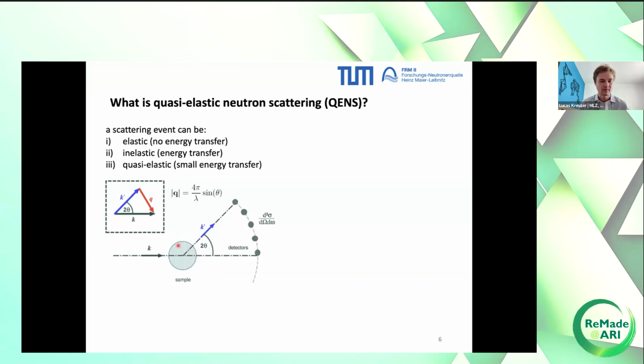Now, just generally how QENS would work. Again, you have an incoming neutron, which is interacting with your sample. It gets scattered. And by having the incoming and the outgoing neutron wave vector, you subtract them, just like we did with the reflectometry, you get the scattering vector Q, which tells you something about the length scale. But you can measure a second thing. If you know the wavelength of your incoming neutron, and then you measure the time of flight of the neutron from the sample, the scattering event, to the detector, then you know if there was any energy transfer occurring at the sample.